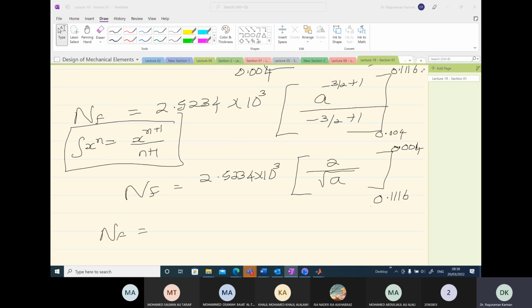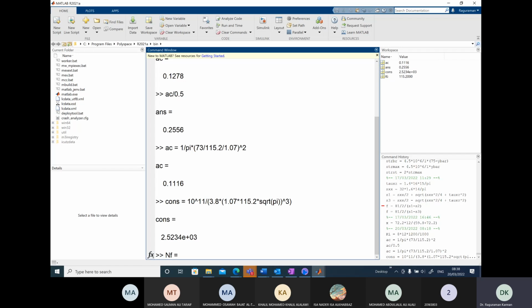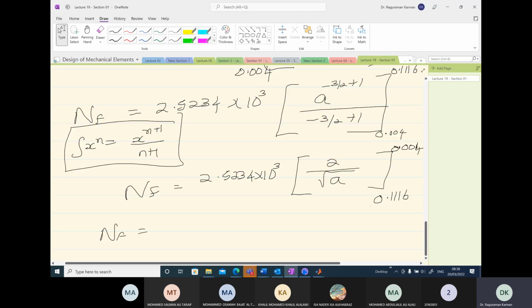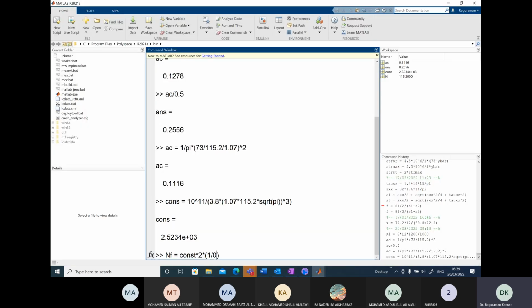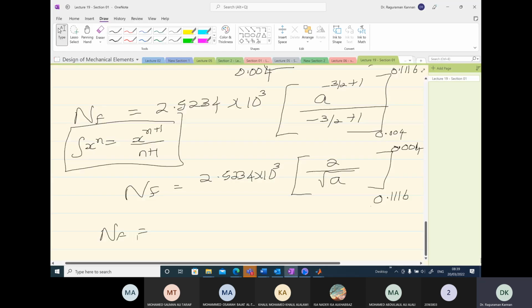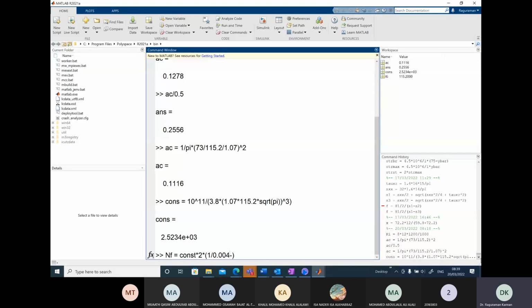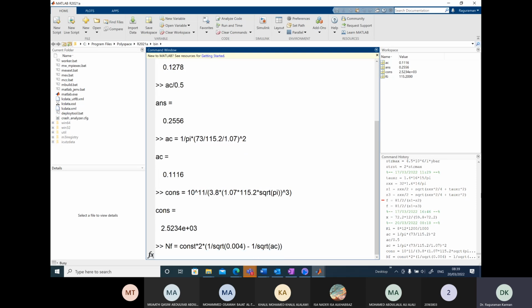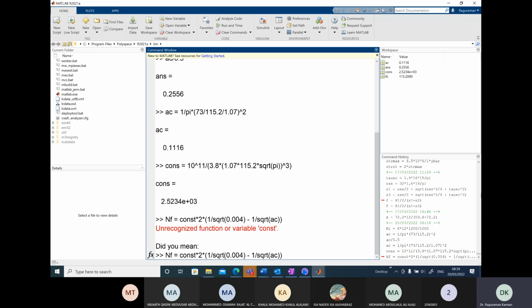So if you calculate f based upon the constant multiplied by 2 multiplied by bracket open 2, we can take it outside, 1 over root a, so 1 over root 0.004, minus, because it is root a, minus we have the critical length, 1 over square root of the critical length, which is AC. Directly use the value, we get